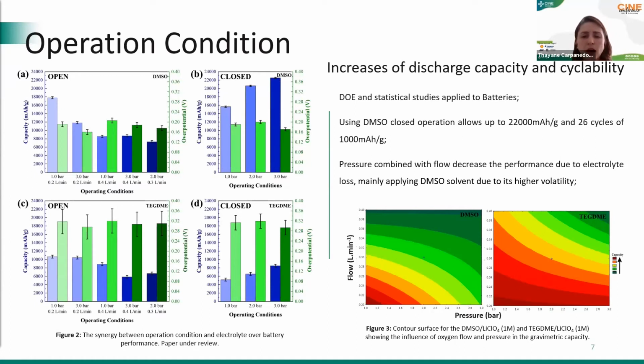Our results point out the same tendency that I showed before. Using DMSO, the closed condition gives the better results. And here we achieve even better capacity values, up to 22,000 mAh per gram, and up to 26 cycles of 1,000 mAh per gram.